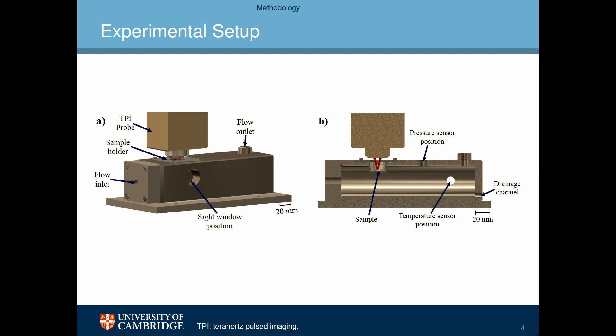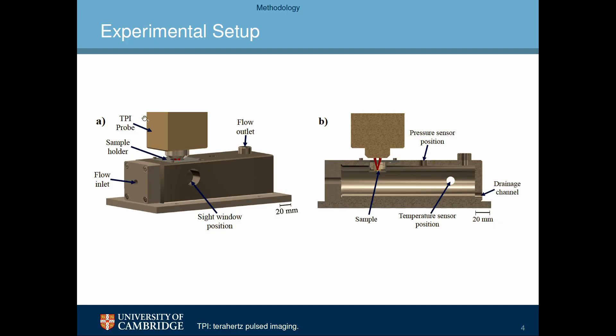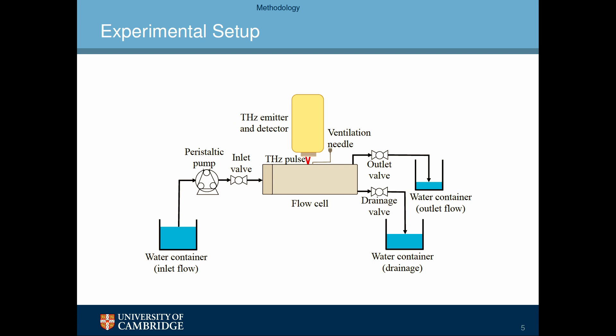The experimental setup used for studying the water transport kinetics in the alpha alumina powder compacts consists of a terahertz pulse imaging system with a customized flow cell that I designed, and these are schematics of the design of the flow cell. Looking at the process flow diagram, we have a peristaltic pump that is used to pump the water through an inlet valve to the flow cell, a terahertz reflection probe to emit and detect the terahertz signal, and a ventilation needle to allow the removal of air trapped above the sample after closing the flow cell. This ventilation process is required to avoid a two-phase flow, as air needs to escape the system upon the transport of water into the sample. Finally, we have an outlet valve to control the outlet flow and a drainage valve to control the waste flow and drain the flow cell once the experiment is finished.